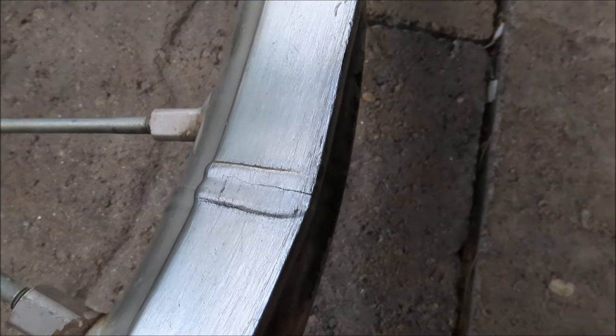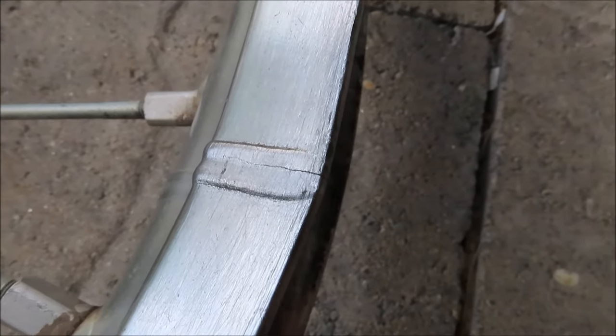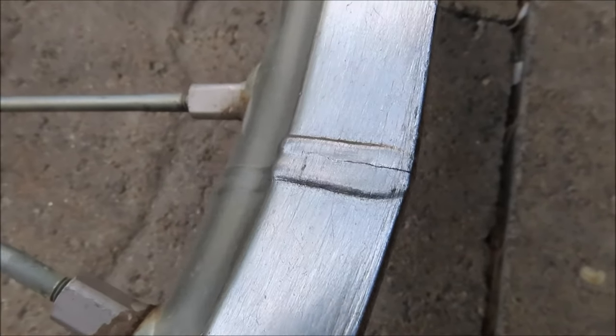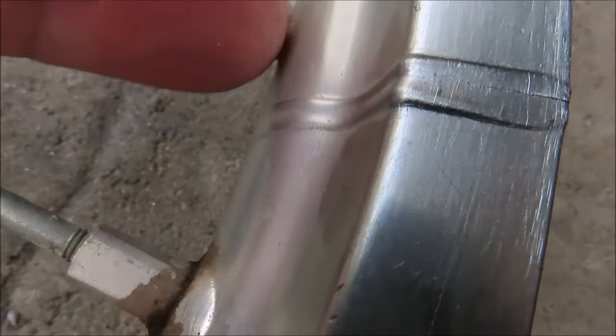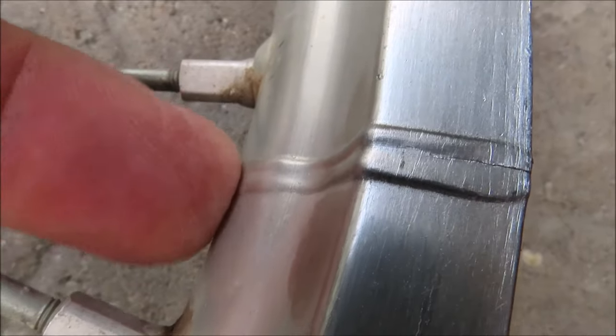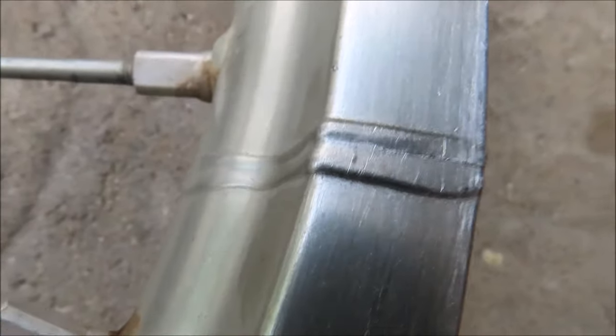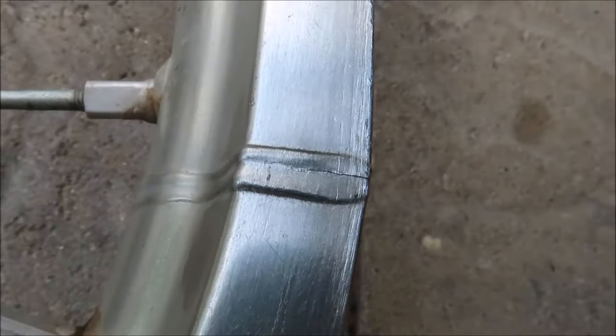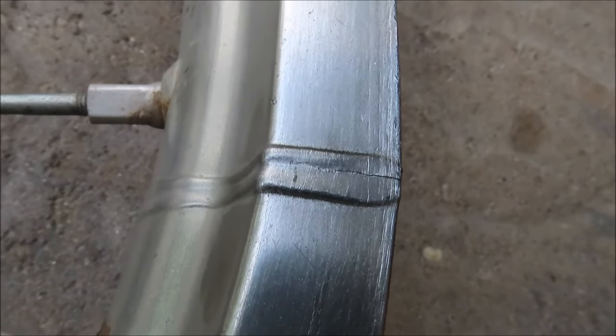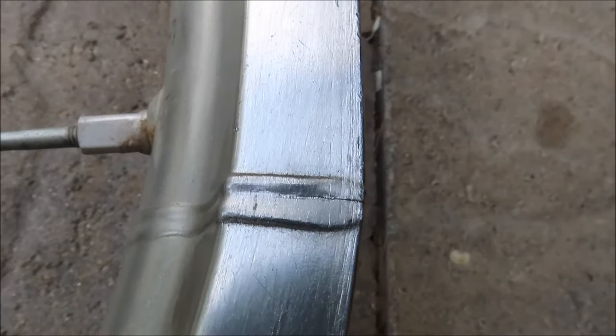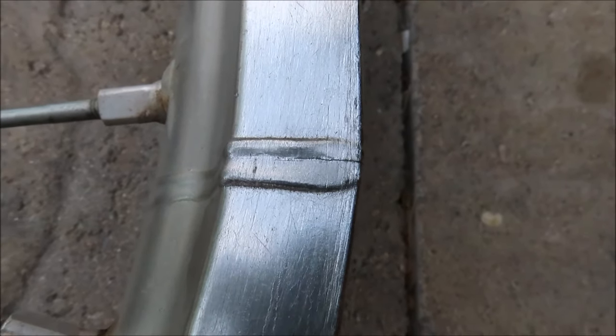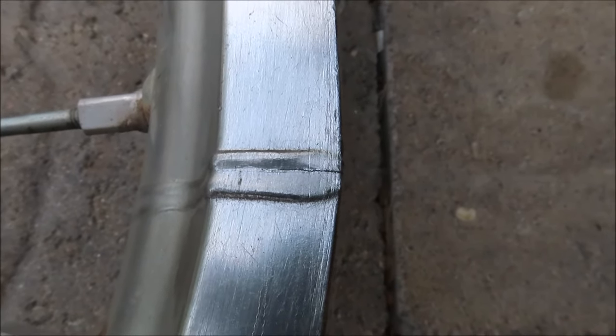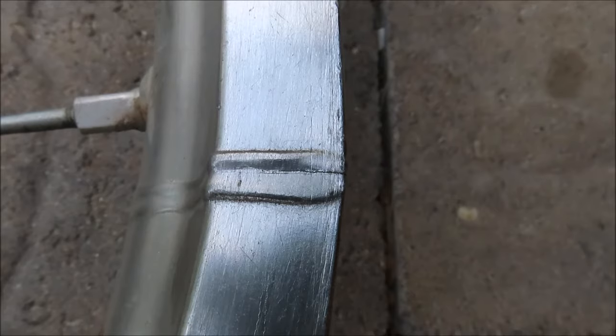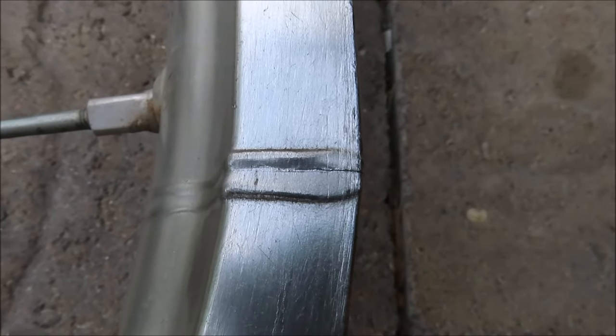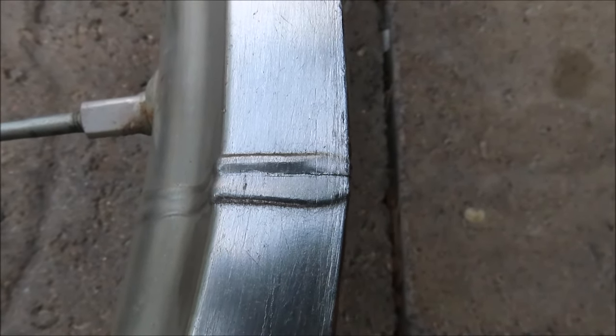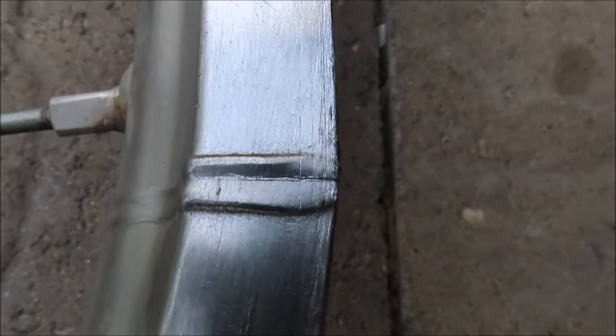So the crack is definitely still there, but it's pulled tight now. And it has this whole lip here. It's raised up just a little bit. I'm not an expert at welding. I'm not sure exactly what material this is. It's supposed to be an aluminum rim as far as I know, but it must be mixed with some other alloys. We got it up to about 560 degrees and it would not melt the aluminum welding rod, whereas on the test runs it was melting at around 450.